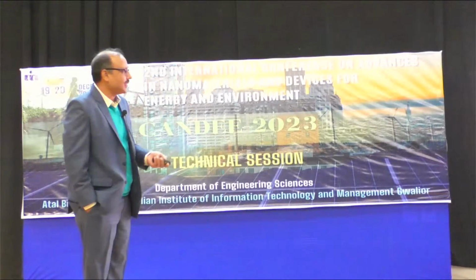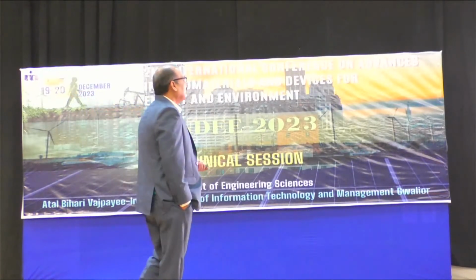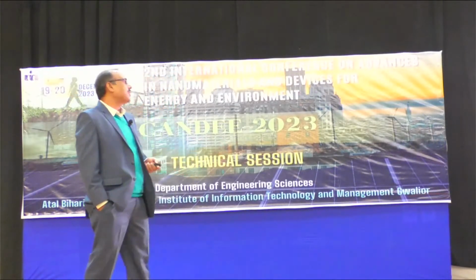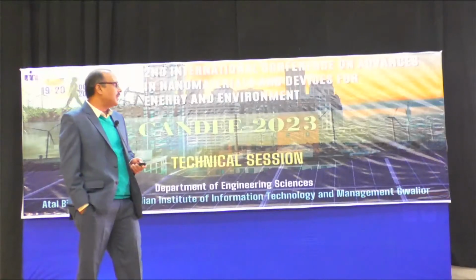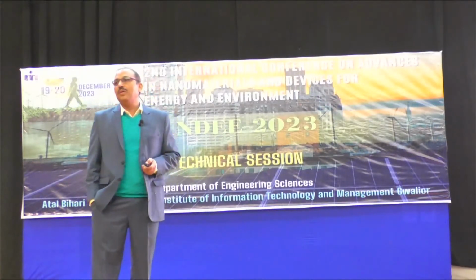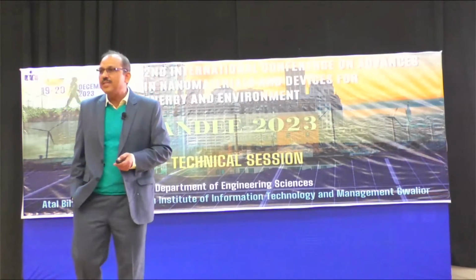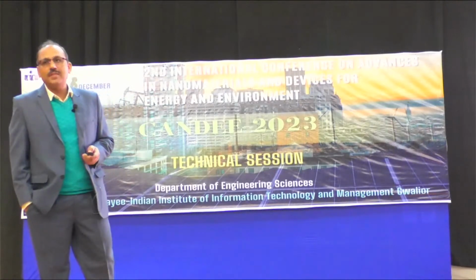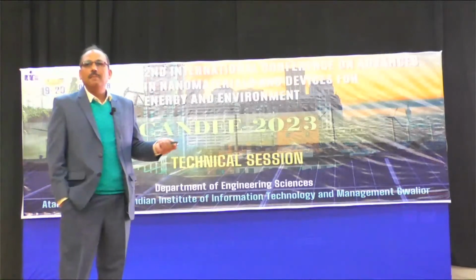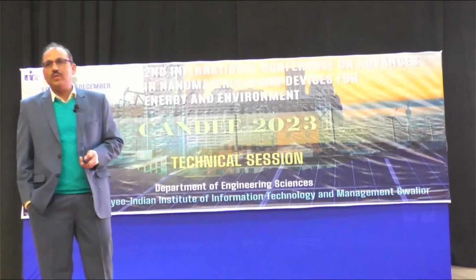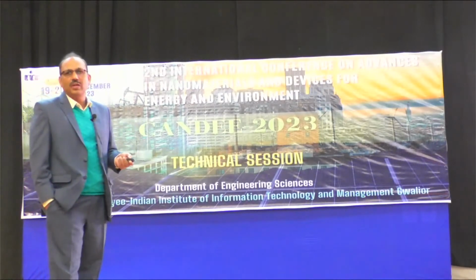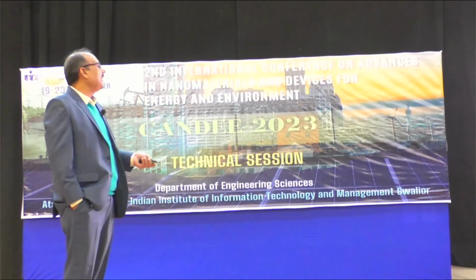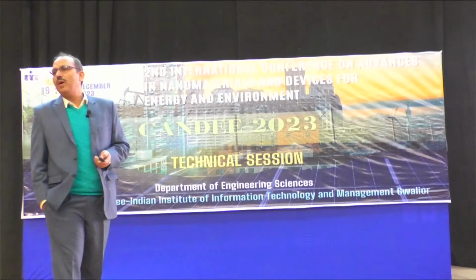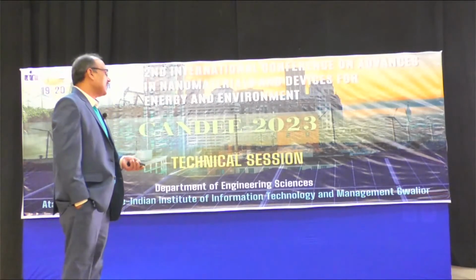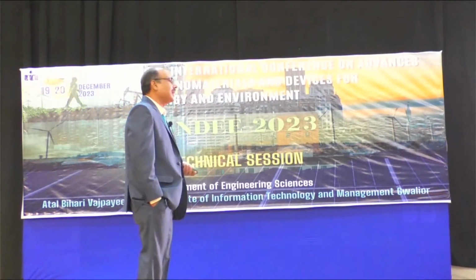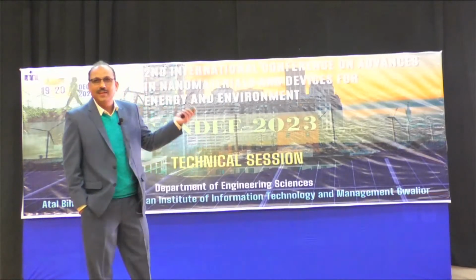That is important. You can see here the hydrogen adsorption kinetics. When we took 10 weight percent of magnesium, we got nearly 1 weight percent hydrogen. That is not great, since people have reported nearly 2.4 weight percent in such systems, but we got only 1%. When we increased the magnesium, it was nearly 0.8% only. So it is not a very impressive result, but we got good qualification anyhow.